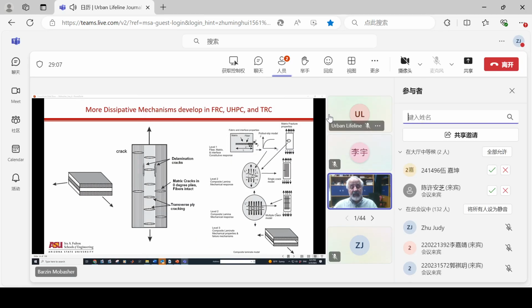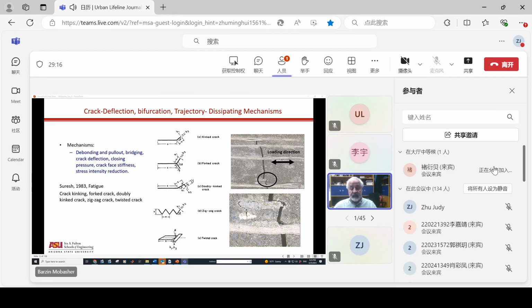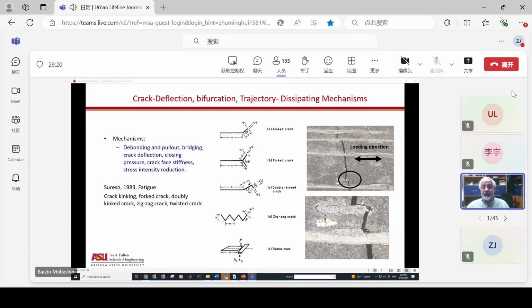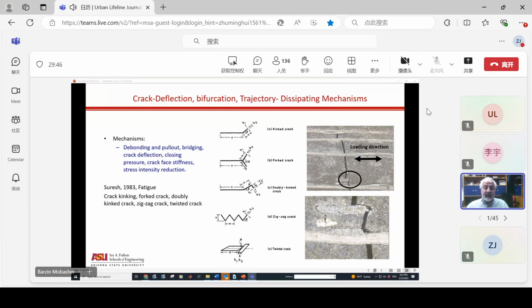And if you double or triple the strength in tension, you can definitely reduce the amount of concrete that's needed to carry a certain amount of load. That becomes secondary and we can calculate it. Another part that I showed you is how a crack gets bifurcated, gets deflected, and then travels. So this is basically all of the delamination that I was showing you in a picture. All of these parameters can be shown to be mechanisms that form in the case of fatigue of metals, and that's how fatigue can be calculated in terms of how much damage you're allowing to take place inside the material. You don't want to have a clean, fresh crack that's growing. You want to basically make it difficult. The best example of it would be continuous fibers.